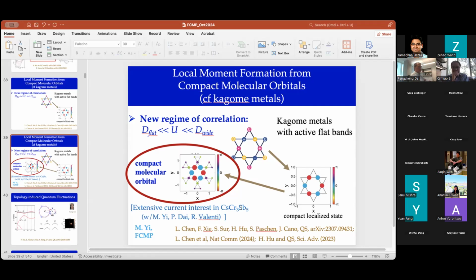We see a band which disappears in field and temperature with a very large change of conductivity, and with a Hall effect which disappears in a very short increase of temperature or field. So it's obvious that we have something very narrow, and as it is an orbital Kagome structure, it's obvious that you will have the flat band. Well, we are not sure that we can use the single orbital Kagome to get the band structure that you show, but okay. Maybe some people will be able to do careful calculations to show that. I have not been successful in driving people to do that, but the experiments are beautiful.